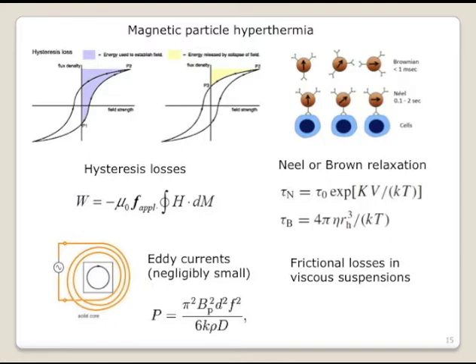There are several processes that happen during the magnetic reversal that generate heat. The first one is called hysteresis loss, just like the electromagnetic wave used in the home for cooking. If you have a ferromagnetic material and apply AC current, they will reverse the magnetic field. Each time they lose some energy as heat. Right? The heat generated is proportional to the frequency used, and also proportional to the magnetic field strength you applied to the ferromagnetic material.